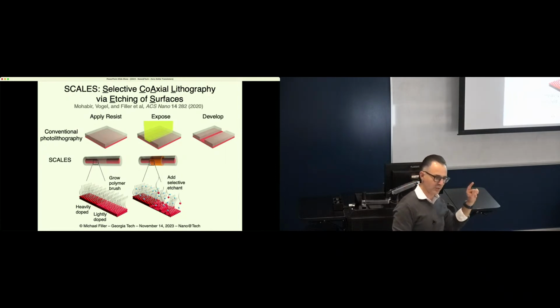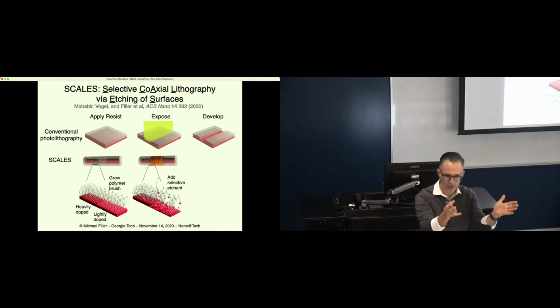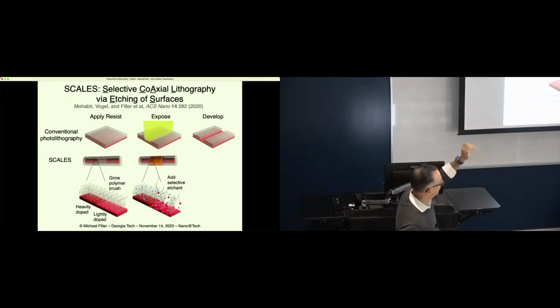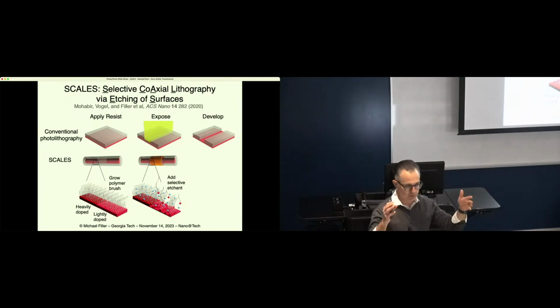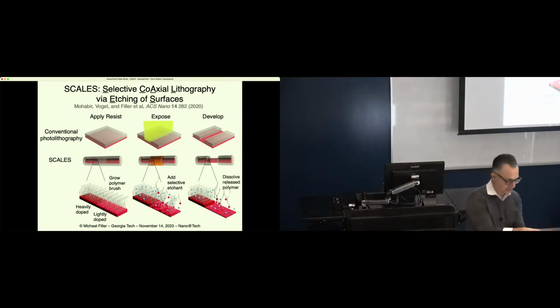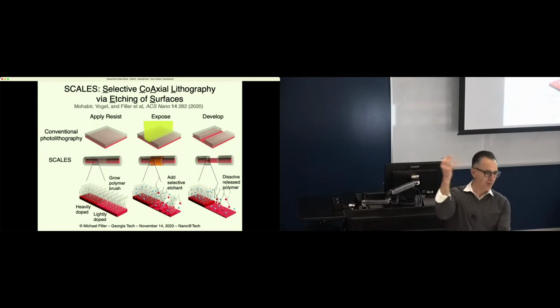It's pretty similar to the one I had shown on a previous slide to make those undulating structures. But if you design the chemistry correctly, it will diffuse through this polymer, and it will find the underlying semiconductor. It will find the nanowire surface, and it will etch the lightly doped channel region, and it will not be able to etch the heavily doped source drain regions. And when it etches that channel region, because it's removing some silicon atoms from the surface, that's where the polymer is tethered to, now the polymer breaks free from the surface and can be solvated in solution.